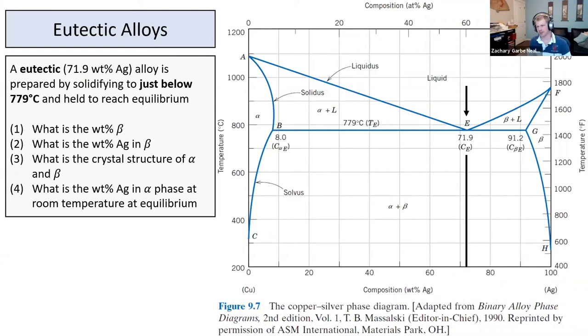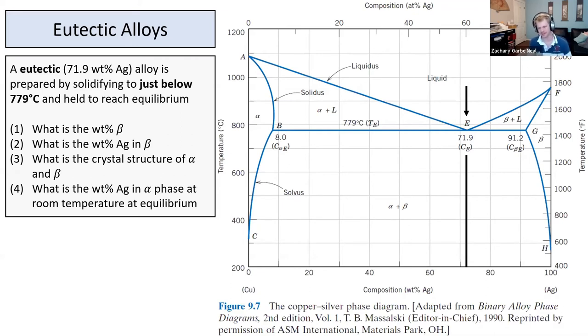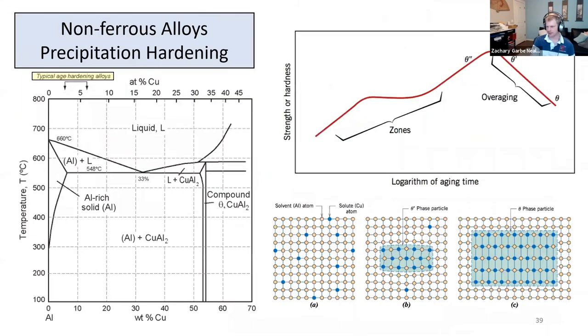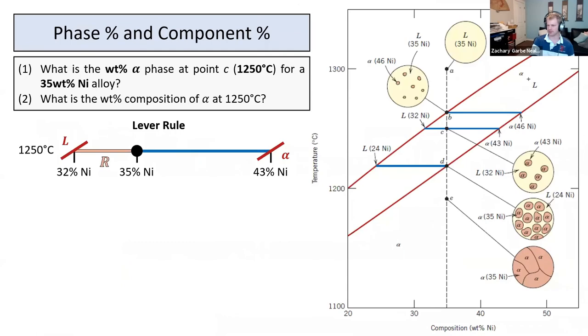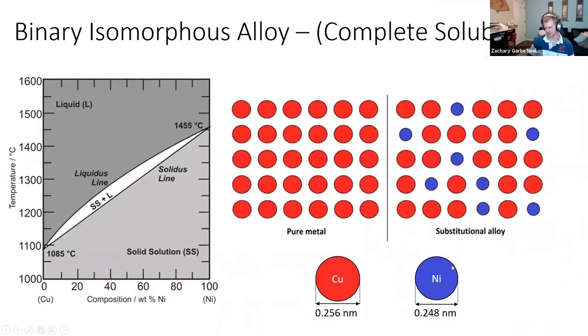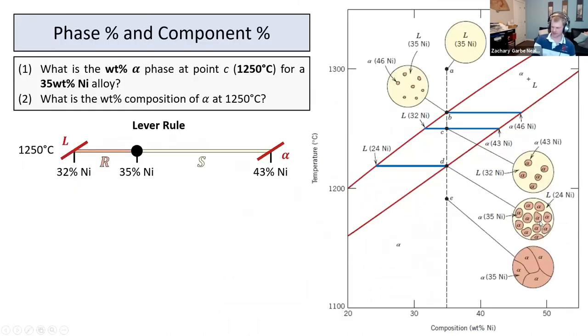Kinetics are also a factor — we'll see that more with steel. If you synthesize an alloy at 600 degrees, you'll have some solubility, and then if you quench it rapidly to room temperature, you won't give enough time for atoms to diffuse. So you might be stuck with some silver inside the alpha phase even if that's not at equilibrium. We call that a metastable or non-equilibrium phase. In steel, that happens all the time.